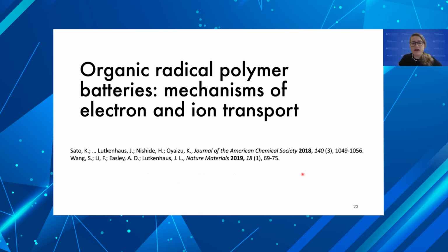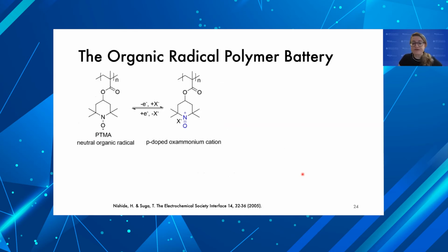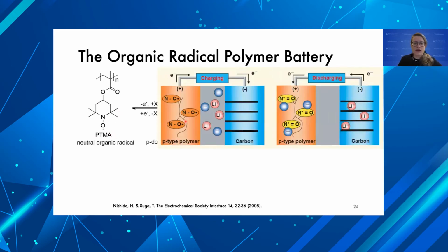So I'll start with talking about how these polymers transport electrons and ions. I hinted that it's really different from what you've seen before. As a platform, we're going to talk about this in the context of this polymer PTMA. If we put PTMA in a battery in one of its first constructs in 2005, it would look like this, where the anode and the electrolyte are still the same as a regular lithium-ion battery, but we switch the cathode out with the PTMA. As we charge and discharge it, the PTMA becomes positive, and then we're actually exchanging anions instead of lithium cations. So it's a bit different.